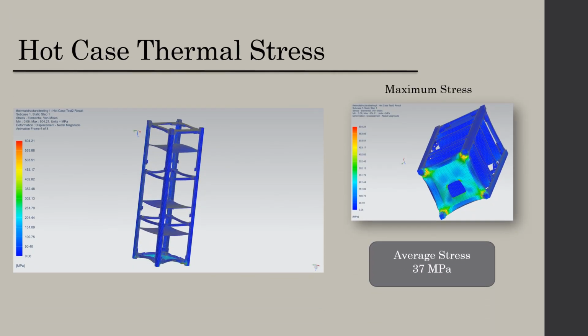Similar to the cold case, once the temperatures were output for the hot case, they were mapped to the structural model of the CubeSat and the stress was output. As seen here, the average stress was smaller than the cold case at about 37 megapascals. As stated previously, the yield strength of aluminum at 100 degrees Celsius is about 260 megapascals. Therefore, the model will be able to survive the hot case thermal loads.